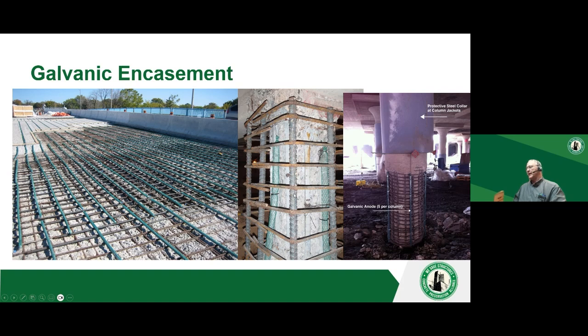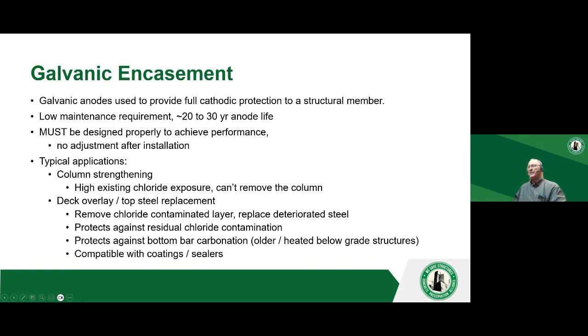And here's the galvanic encasement. This is another galvanic encasement. And in these cases, you're probably going to get 20 to 30 years of anode life. You're not going to get your 75 or 100-year anodes, otherwise you'd have very large anodes and it would be cost prohibitive. So you typically get 20, 30 years out of it.